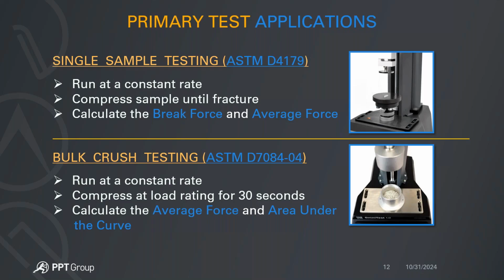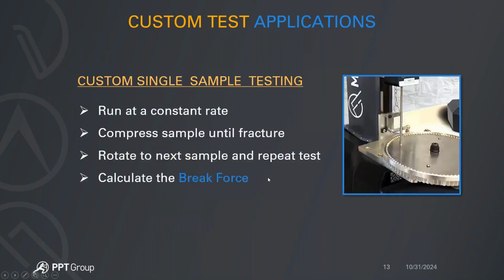Now, in cases where you're testing single samples, you also want the ability to test as many of them as possible, let's say 100 at a time, instead of having an operator always pick and place the single pellets. There is a custom semi-automated solution that has a carousel that allows you to test these multiple samples by running at a constant rate, compressing the sample until fracture or break, and then the test completes and rotates to the next sample, repeating the test for as many samples as you have, whether it's 10, a dozen, 50 or 100. And in most of these, especially when you're only looking for just the break force as a value, you should be able to calculate that.